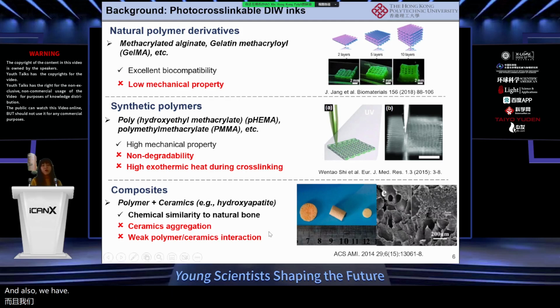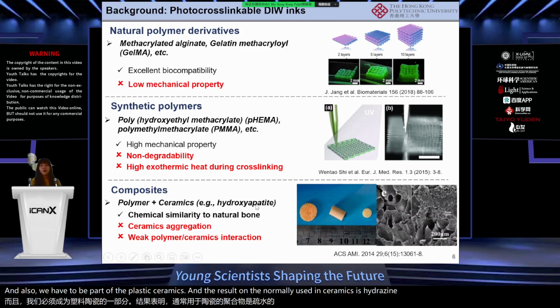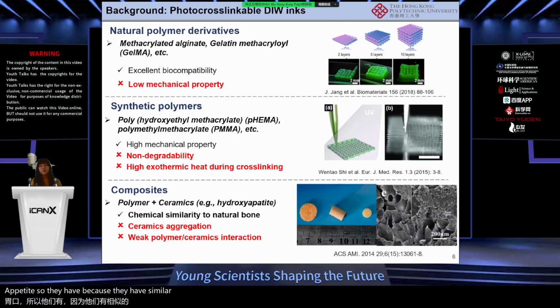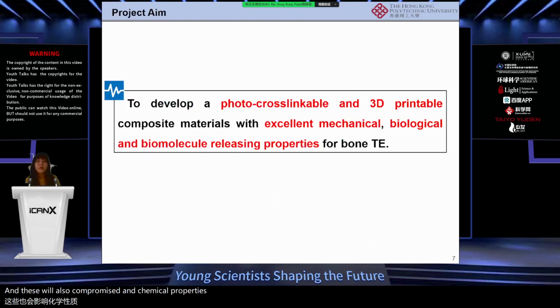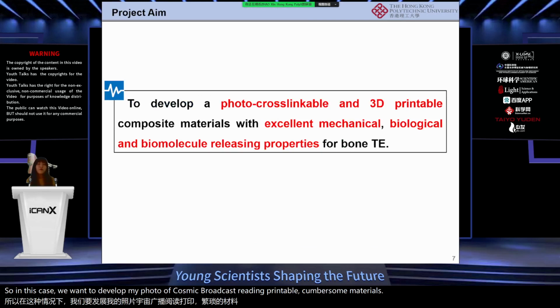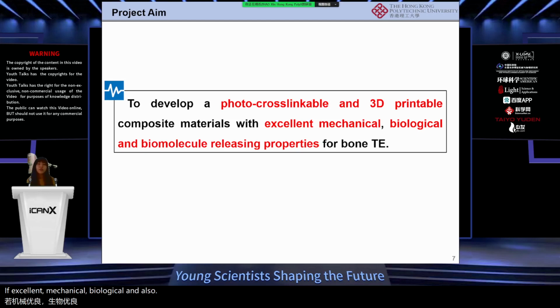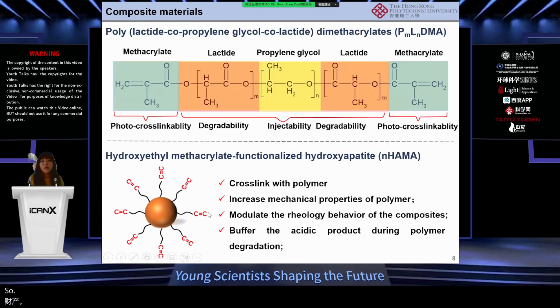And also we have polymer plus ceramics. The normally used ceramic is hydroxyapatite, because it has a similar chemical structure to natural bone. The problem is that the hydroxyapatite nanoparticles, because the particles are very tiny, might aggregate. And also the interaction between the ceramic particles and the polymer is not very good, and this will also compromise the mechanical properties. So in this case, we want to develop a photocross-linkable and 3D printable composite material with excellent mechanical, biological, and also biomolecule releasing properties.